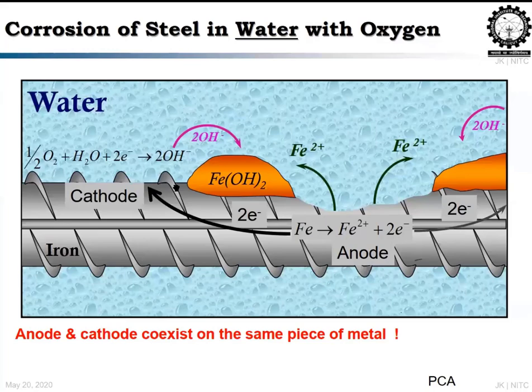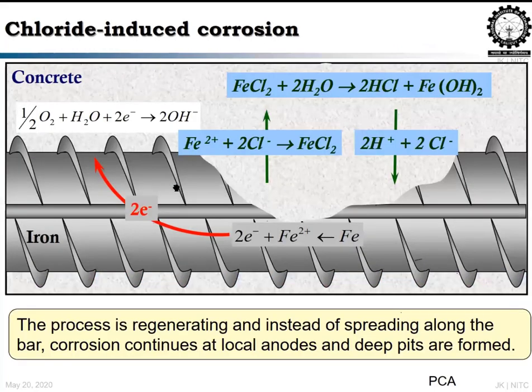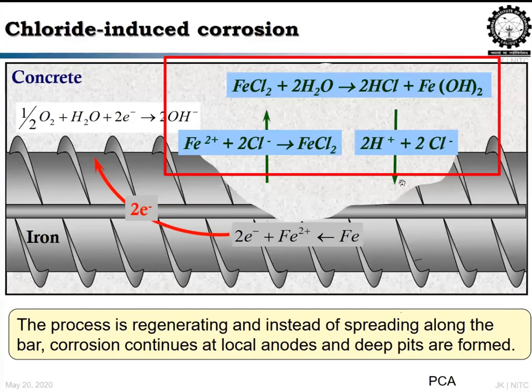Where we should be very serious is chloride-induced corrosion. Why? Because here the Fe2+ ions that come out of corrosion will react with the chloride present near the steel surface and form ferrous chloride, and that ferrous chloride will react with the moisture and form ferrous hydroxide, the same compound formed in rusting. In addition to that, it will form HCl, which we know is hydrochloric acid. Obviously, that acid will reduce the pH. Then, what is the major issue?